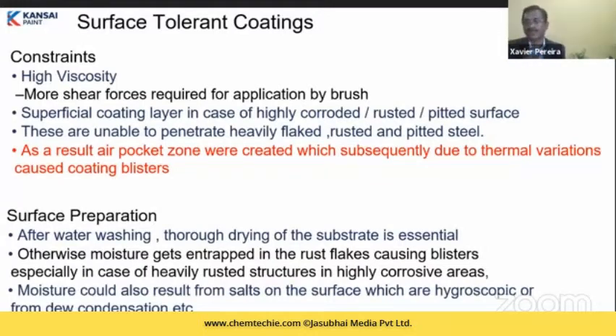So when you apply a thick coating on a rusted surface, you get air pocket zones, which subsequently, because of the variance in temperatures, the outside temperature and the substrate temperature, you get blisters. Okay, so that was the cause for the air coming out as blisters. Secondly, normally, all paint experts recommend thorough water cleaning of a rusted surface. Right, now after water washing, thorough drying of the substrate is essential. Otherwise, the moisture gets entrapped in the rust flakes and they cause blisters.